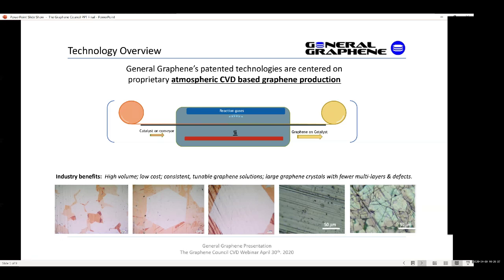So our process is relatively flexible. We don't have the confines of vacuum, and this allows our scientists and technicians to tailor the crystal size, its coverage, the number of multi-layers and defect levels, and to tune those. With this process flexibility, as I said, we can tune the properties to meet the needs of the specific application. So the resulting graphene is very useful for barrier films and filtration media and demonstrates additional useful properties, including transparency and conductivity, strength, and lubrication for other applications.